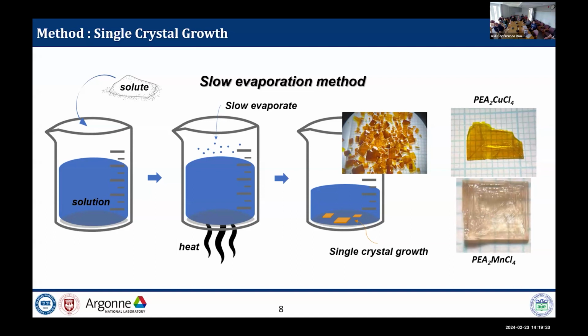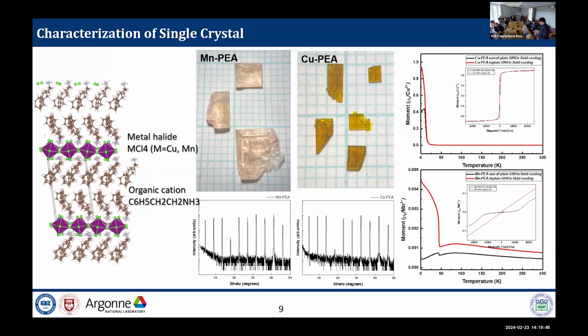So we can get a transparent bright yellow single crystal of PEA2 copper tetrachloride and a transparent pink single crystal of PEA2 manganese tetrachloride. We confirmed these materials as single crystals with lab XRD and SEM EDS measurements, magnetic property measurements, and high temperature DSC measurement.